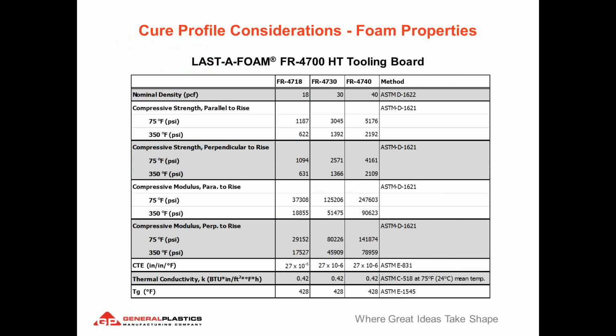So cure profile considerations. Actually, go back to a little more about density as we move through that. At room temperature, the 18-pound versus 40-pound is almost a factor of 4 difference in compressive strengths. So as the temperature goes up and perhaps your curing pressure goes up, the higher the density will maintain its dimensional stability better. So as you increase the pressure or forces on that foam, the higher the density will be more resistant to any kind of deformation from external pressures or stresses. We also pay a price and cost for that higher pressure, higher density.